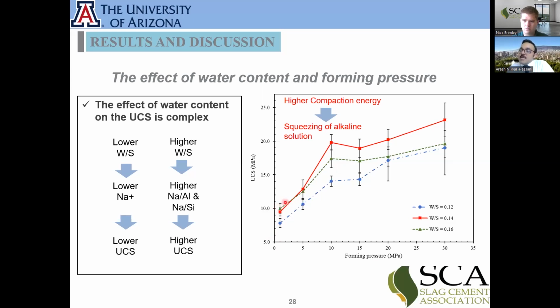That means in lower compaction energy, the liquid is there, and higher liquid means we have a higher amount of sodium hydroxide and sodium silicate. And when this is higher, the alkalinity of the media is higher, the pH is higher, then we can dissolve more silica and alumina from the mine tailings and slag. And then we can have a better geopolymer.